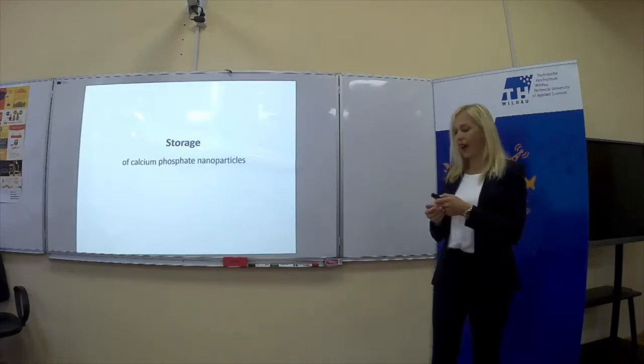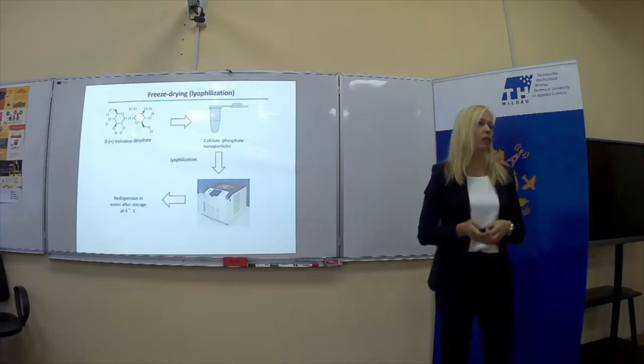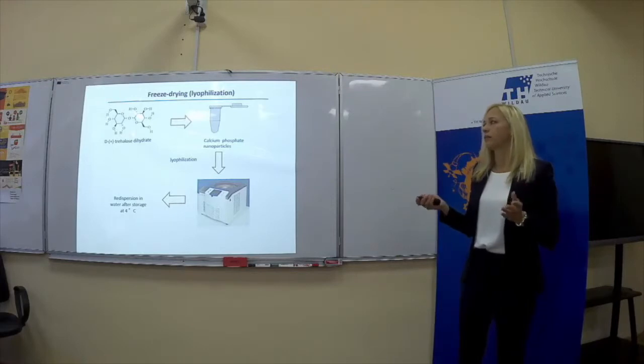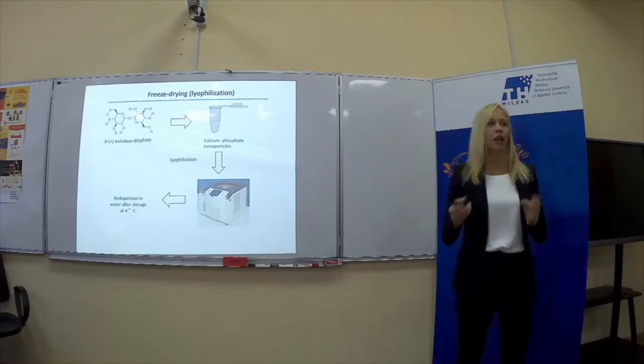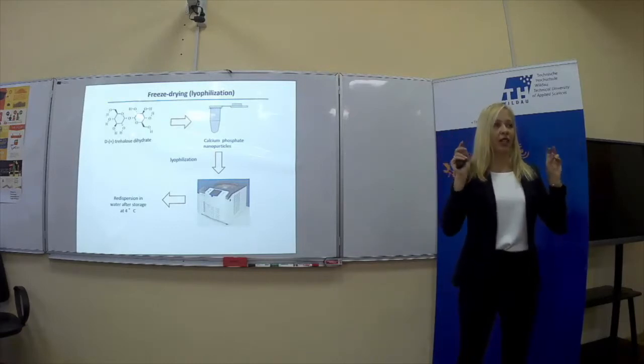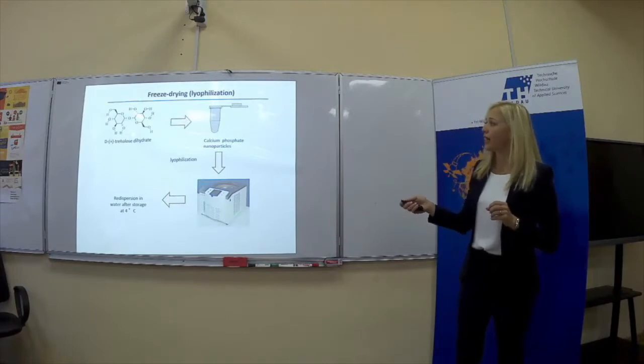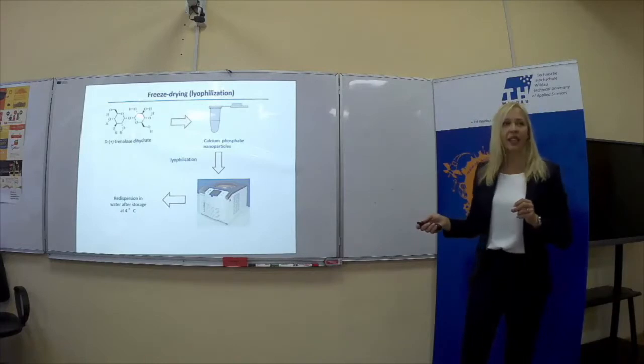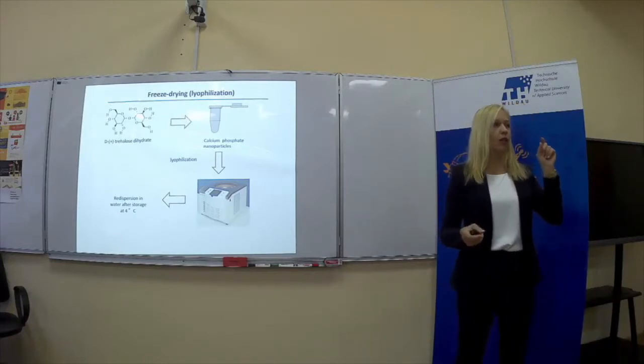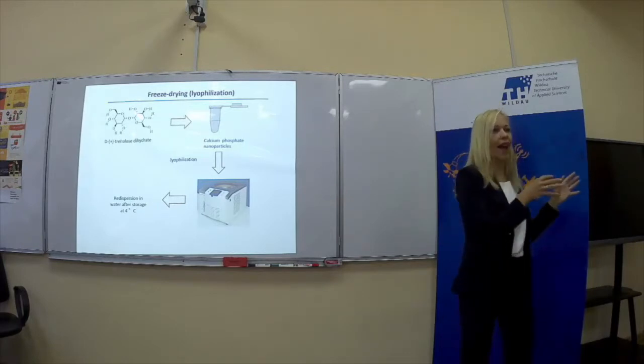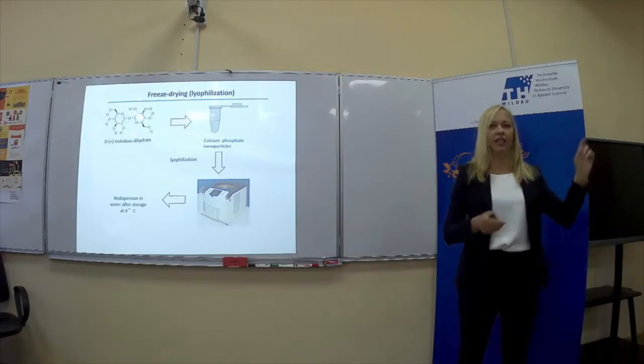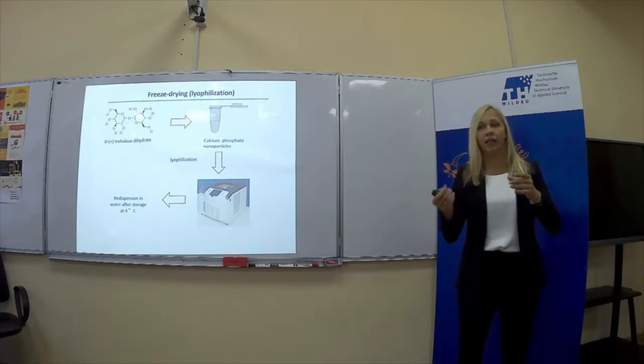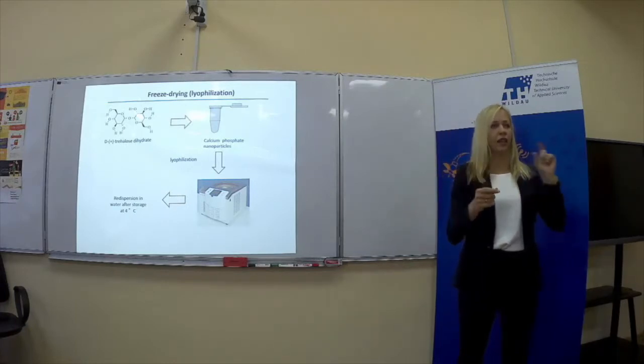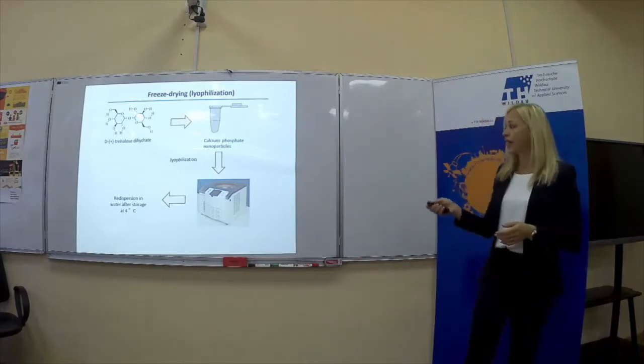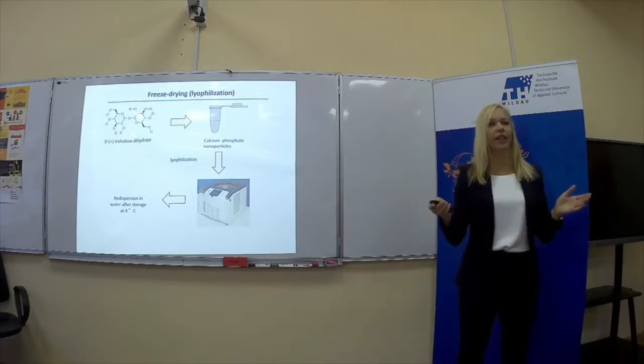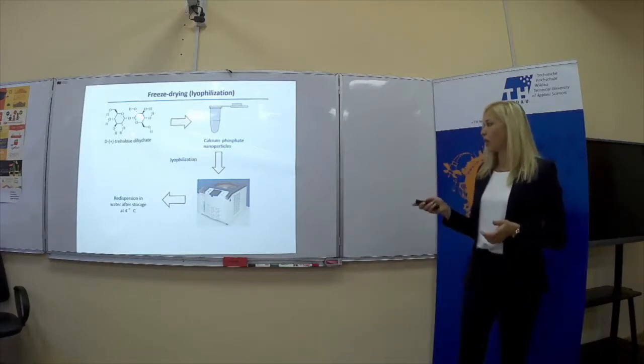We wanted to make sure, and we developed one method, which is also used everywhere, so we just decided to apply it to our nanoparticles. What you usually do with your colloid is add a matrix. This is trehalose. And as soon as you have such nanoparticles with trehalose, you can do lyophilization, and at the end you just get a powder of calcium phosphate in this matrix. And this is stable forever, I would say. So you can take this powder and send it anywhere in the world, and a cooperation partner can just add the original volume of water, redisperse it, and use it for biological experiments. So after developing this storage method, it was very easy to send or bring nanoparticles all around the world.